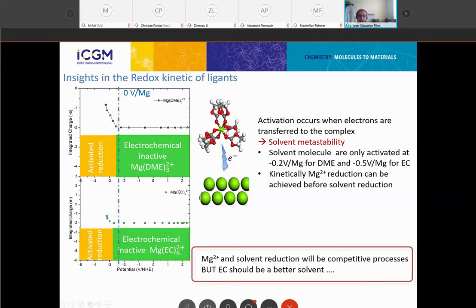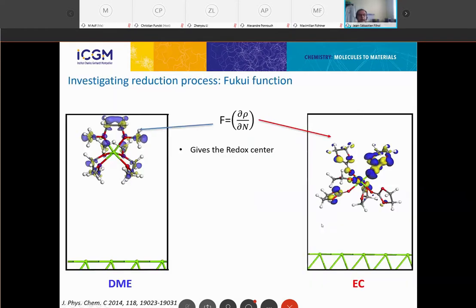For ethylene carbonate, it's about the same, but ethylene carbonate should be quite better. The electro-inactive zone is slightly larger around magnesium, so ethylene carbonate should be better. But of course, ethylene carbonate is not better, so there's something more to understand. And to really understand, we need to focus on where the reduction just occurred.